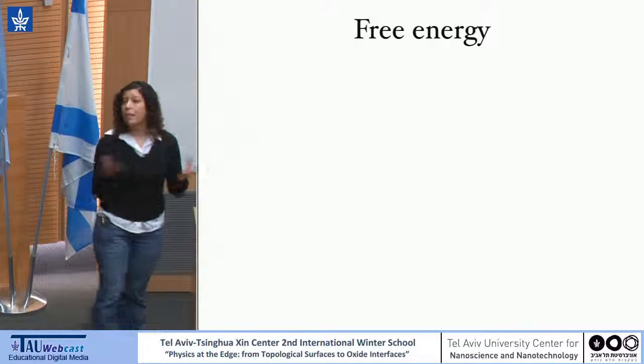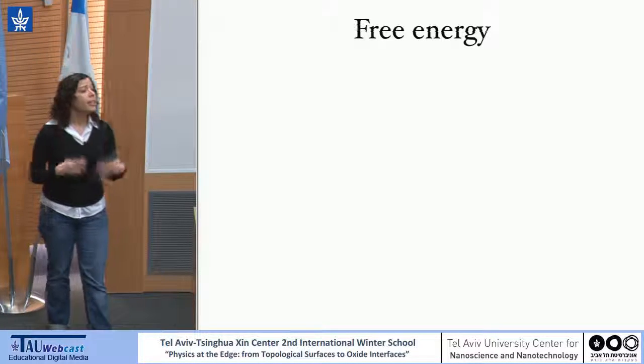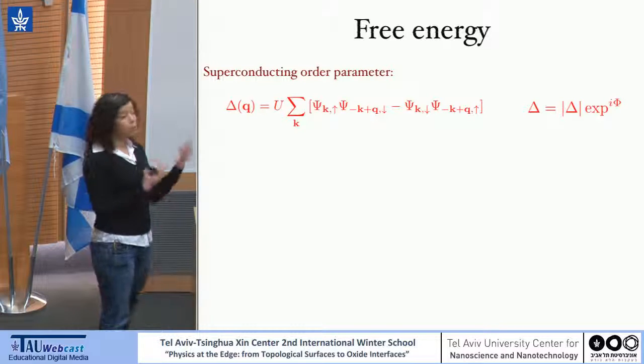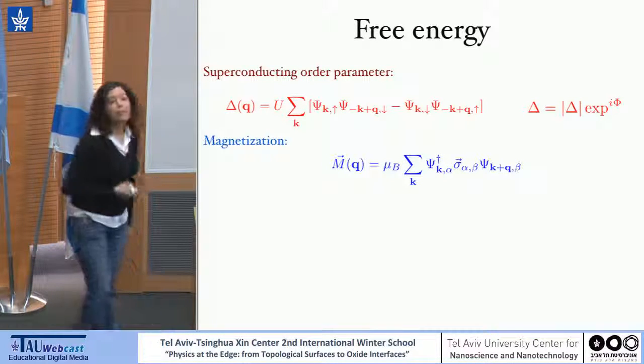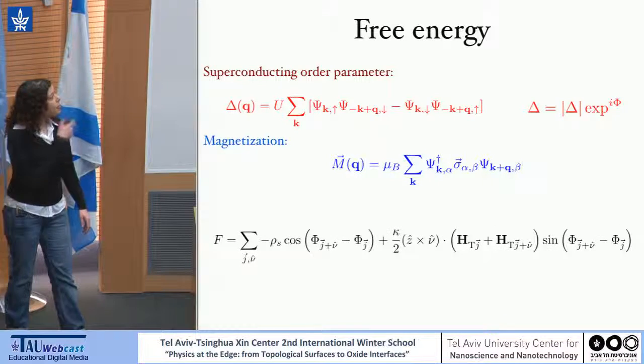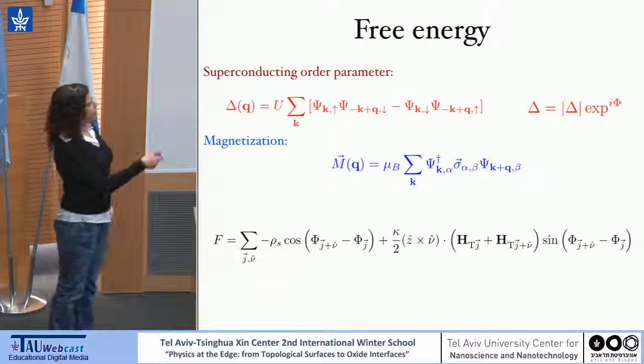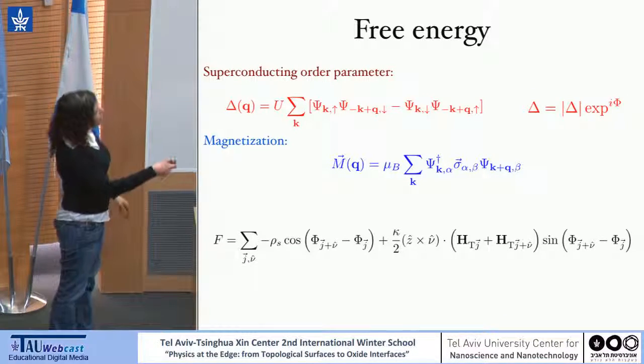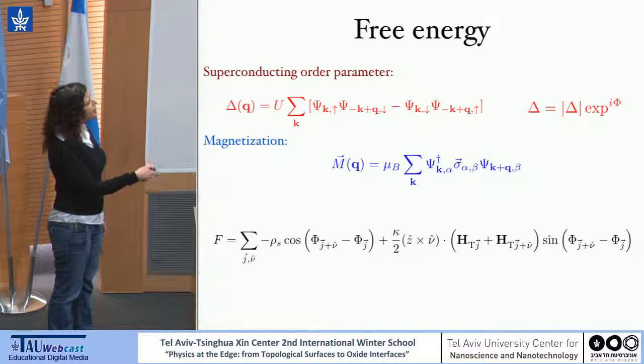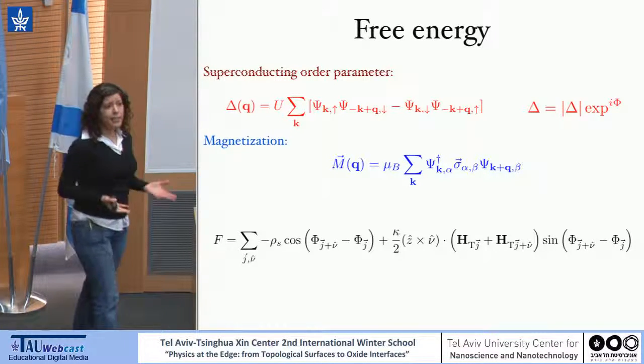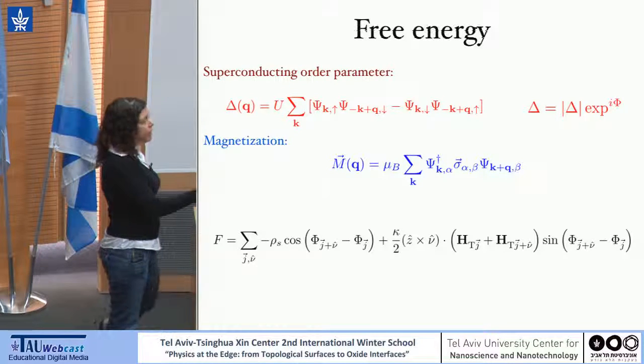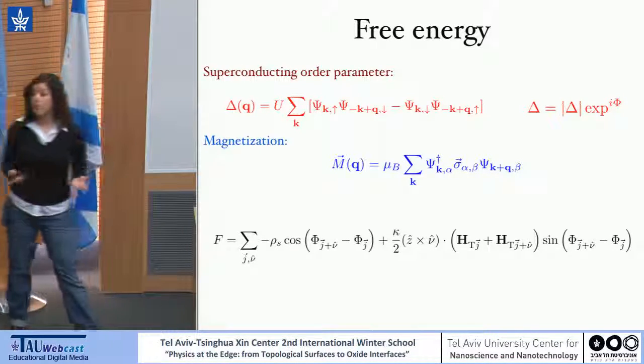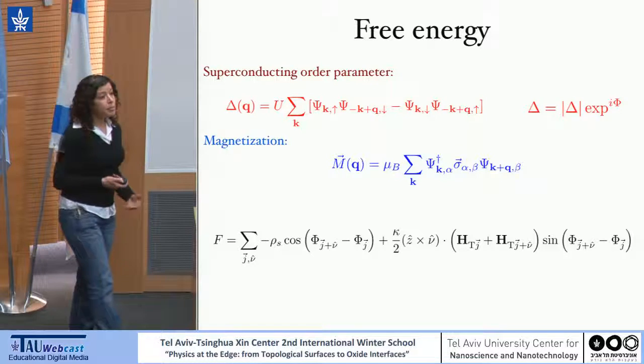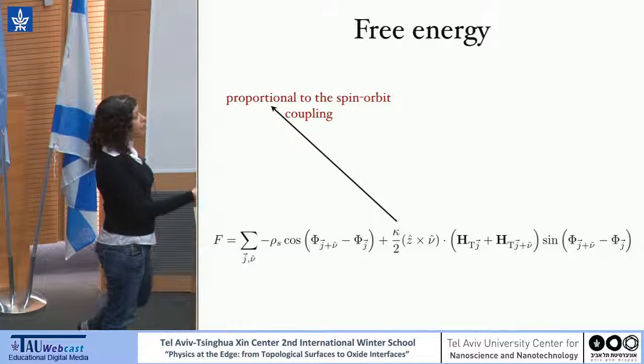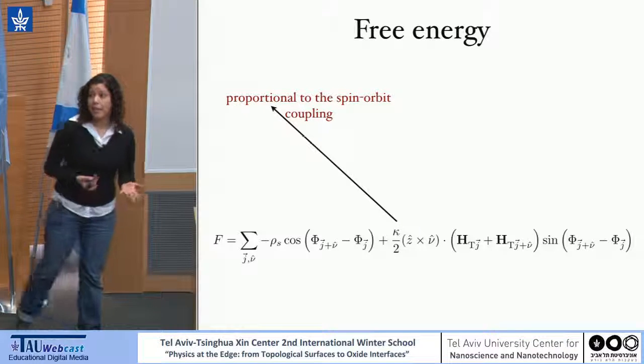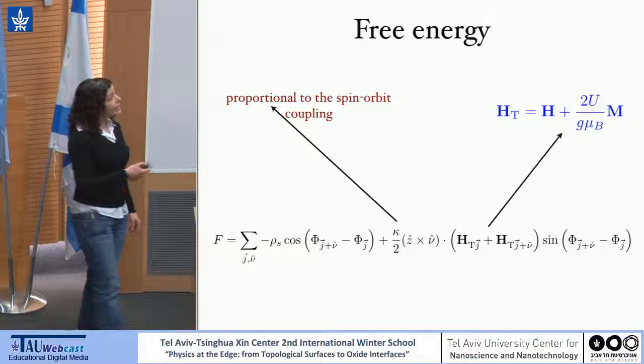We will look at some kind of macroscopic picture of the free energy in the presence of both superconducting order and magnetization. When we look at the free energy of such systems, you can recognize the regular phase-only free energy, the regular phase stiffness term. But we have a new term here that doesn't appear in regular superconductors. This new term is due to the spin-orbit coupling. Its coefficient is proportional to the spin-orbit coupling.